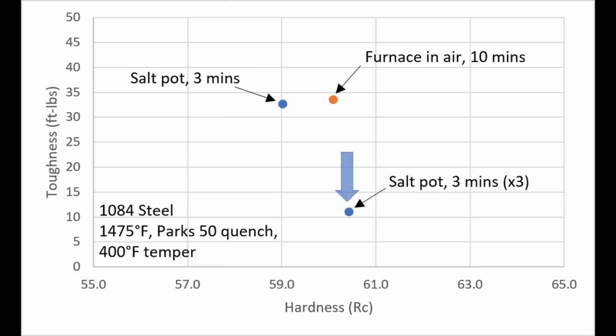Instead, the toughness was much worse when I did this rapid triple quench. The grain size was still incredibly fine, but for whatever reason, the toughness was greatly reduced. And if I had to guess beforehand, I would have said this would lead to better toughness, and so would the average knife maker. But without quantitative testing, we don't know what is improving the steel and what is making it worse.